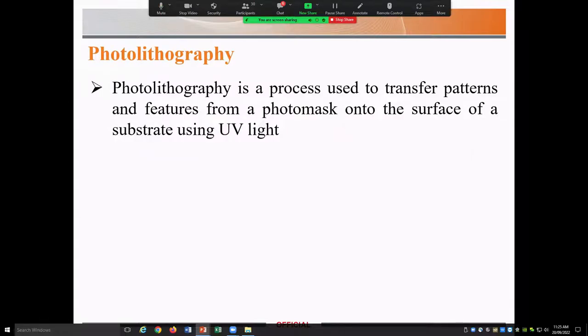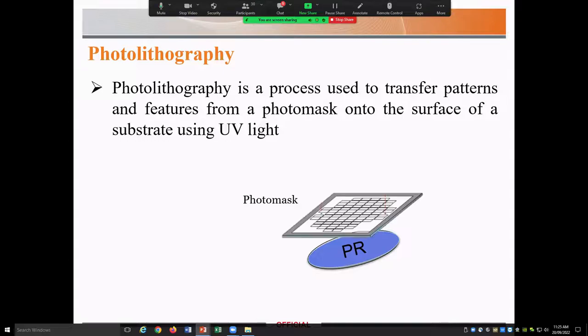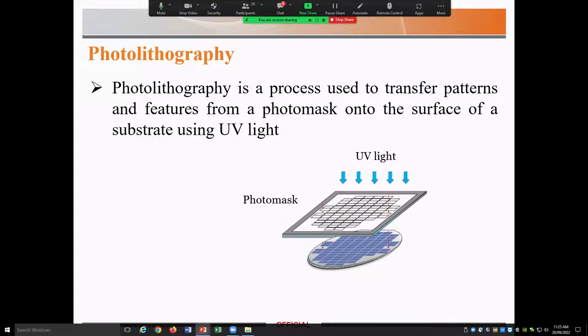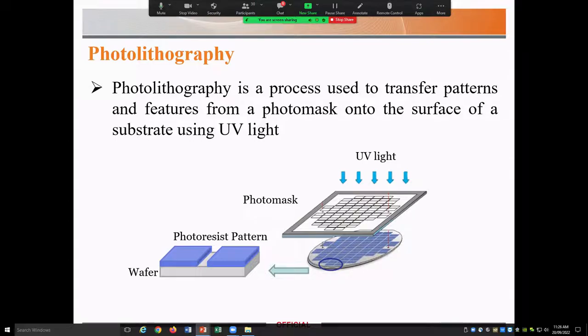So in photolithography, basically the patterns are imaged onto the surface of the substrate using a photomask and UV light. In a simple way, if I want to show how it works, we've got a wafer. We coat it with a photosensitive chemical, which is photoresist, and then we expose this photoresist to UV light through a photomask. Some parts will be exposed to UV light and undergo chemical changes and become soluble, and they can be dissolved away in developing solution later. And that leaves us a photoresist pattern on the surface.